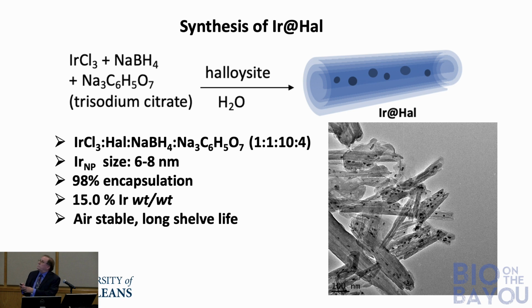But in this case, what we do is basically take the iridium chloride, reduce it into the metal particles in the presence of a capping agent. Now, that capping agent is really important because it coats the nanoparticles and draws it into the tube. Okay, and looking at the image of the material here, you can see these little black dots. These are our iridium nanoparticles in here.